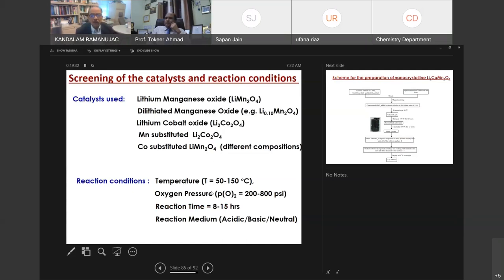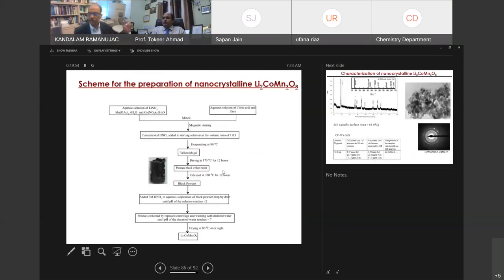We find the most optimal conditions are temperatures between 50 to 150. Industry loves it. Oxygen pressure is slightly high in this case, 200 to 800 PSI, and the reaction time is 8 to 15 hours. We also tried acidic, basic, and neutral media. Mostly basic medium worked very well compared to the acids because we're looking at oxidation. So this is, I don't want to walk you through this chart. This is how the compounds were prepared in nanometric form.